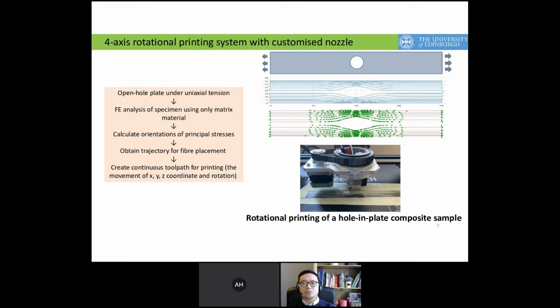To demonstrate this rotational printing system and the powder epoxy filament, we then printed a curved fiber composite. Here we consider a composite plate with a hole under uniaxial tension. We first use finite element analysis to identify the principal stress trajectories in the plate, and then we set out the fiber placement along the stress trajectory lines. G-code is then generated by synchronizing the rotation of the print head with the print path, so that good fiber alignment is achieved at every single position in each pass. Similarly, a laminate can also be printed by controlling the fiber placement in each layer.